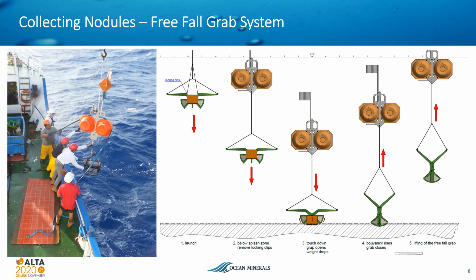When the grab reaches the ocean floor, the grab closes up, collecting the nodules and dropping off the weights. The grab then rises because of the buoyancy from the floats. When the grab system reaches the surface, it is captured by the vessel and brought on board. The grab is then emptied of its nodules. This system was very successful in that nodules were recovered at all 50 drop sites.